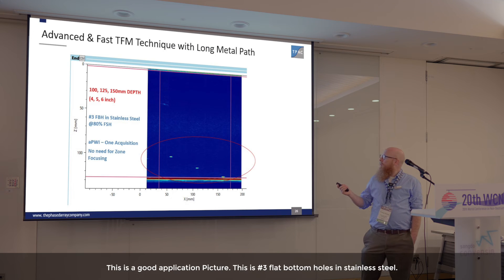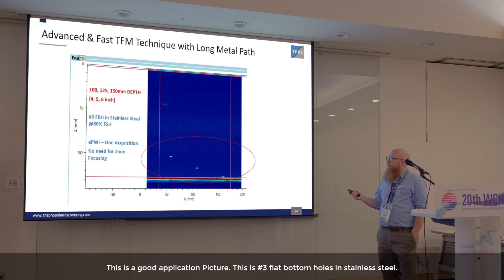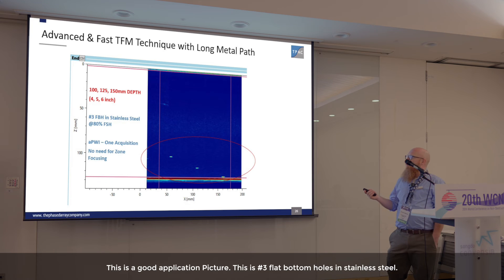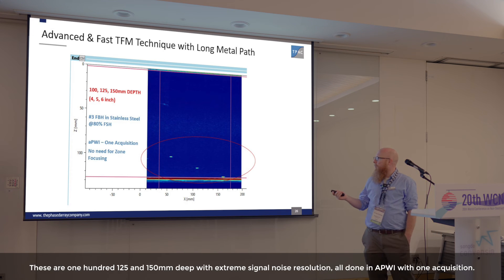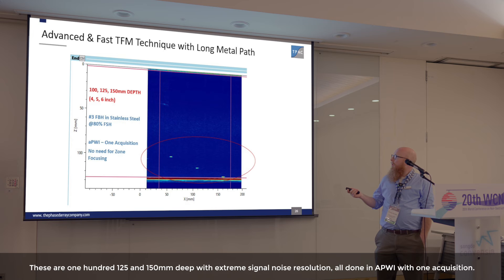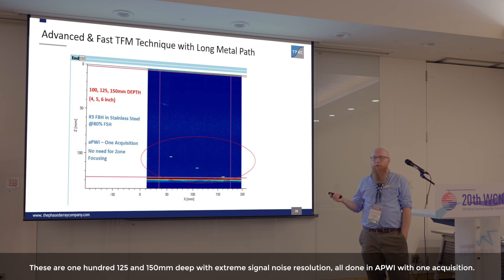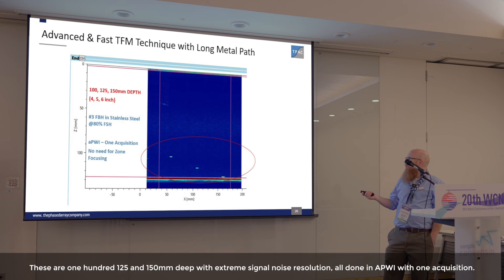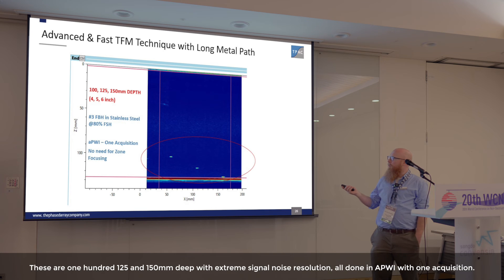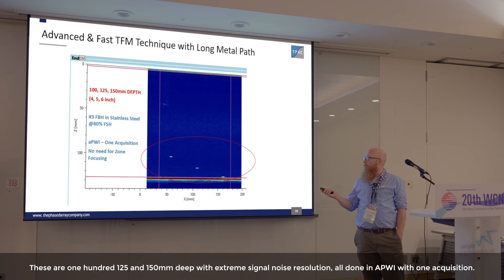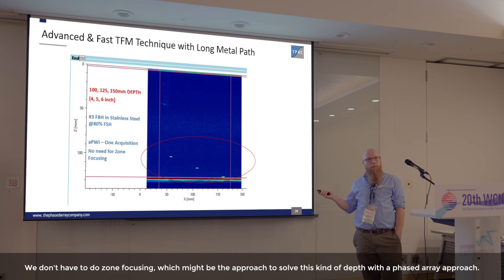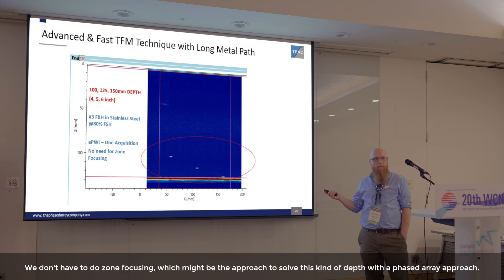This shows number three flat bottom holes in stainless steel at 100, 125, and 150 millimeters deep, with extreme signal-to-noise resolution — all done in adaptive PWI with one acquisition. We don't have to do zone focusing, which might be the typical phased array approach to handle this kind of depth.